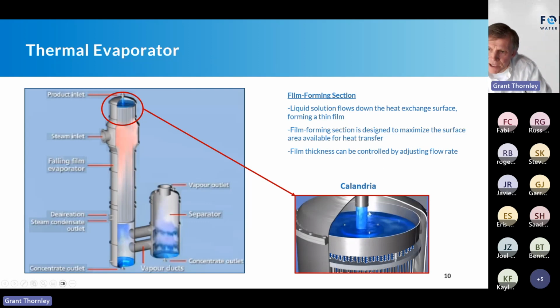How this occurs is that the top of the calandria has a bunch of open-ended tubes, and the solution flows down the tubes. As it flows down the tube, it creates a thin film of that liquid on the inside surface of the vertical tube. On the outside of the vertical tube, we have a steam inlet. So it's a heat exchange. The outside of the tube is being heated. The heat or energy is being transferred through the metal pipe to the thin film. And the thin film, in turn, volatilizes, converting from a liquid to a gas. Pure water comes off. The concentrate drops down to the bottom. As you see here, in falling film the steam goes up. It's captured, it's separated, and the concentrate outlets down there. So a very straightforward process.